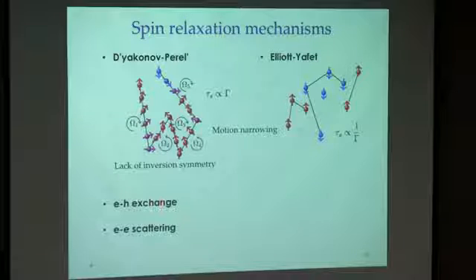In this material, spin relaxation can also result from electron-hole exchange interaction. Although in our measurement, we observe that electron and hole have a comparable spin lifetime, so that we can see the beating of the two frequencies, which is not commonly seen in bulk semiconductors. And of course, electron carrier-carrier scattering also results in spin relaxation. And we have observed that if you increase the excitation power, you get more relaxation.